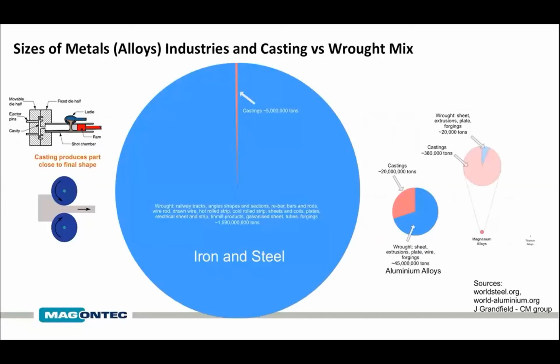We look at the mix of the different metals: iron steel, aluminium and magnesium alloys. This chart shows the area of the circles corresponds to the total consumption in each. You can see that iron steel is huge. It dwarfs aluminium, which in turn dwarfs magnesium. Then if we look within each category, we can subdivide into two categories: castings, where you produce a part that is close to the final shape, and semi-finished or wrought products, such as extrusions, rods, bars, sheets, which are then used to assemble another